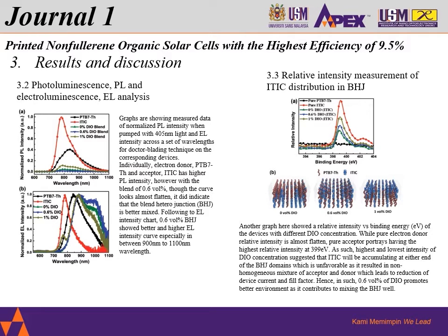Then following the chart at the bottom here, 0.6% of the DIO volume showed a better and higher electroluminescent intensity curve, especially when we're talking about 900 nanometers going towards the 1000 or 1100 nanometers.